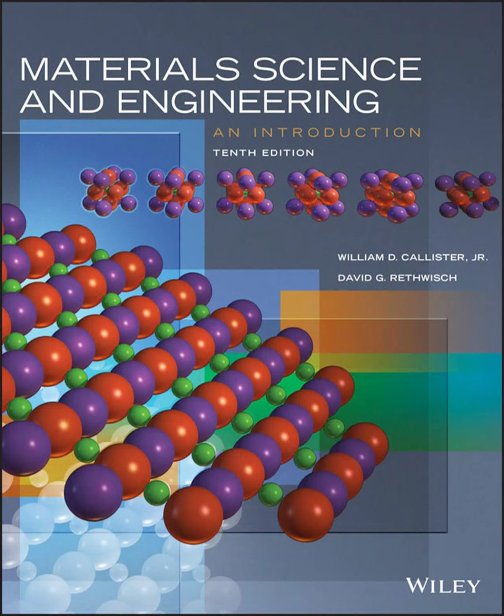Which brings us nicely to the factors that actually influence diffusion speed, that diffusion coefficient D. It's not fixed. It depends heavily on several things. Think of it as controlling the difficulty of that atomic road trip. First off, the diffusing species and the host material themselves are critical. For instance, carbon atoms diffusing in standard alpha iron move much faster than iron atoms moving in that same alpha iron. That's interdiffusion versus self-diffusion. It goes back to the mechanism. Carbon uses that fast interstitial path, squeezing between the iron atoms. Iron atoms have to use the slower vacancy mechanism, waiting for an empty spot. Ah, right. The smaller interstitial atoms have an easier time.